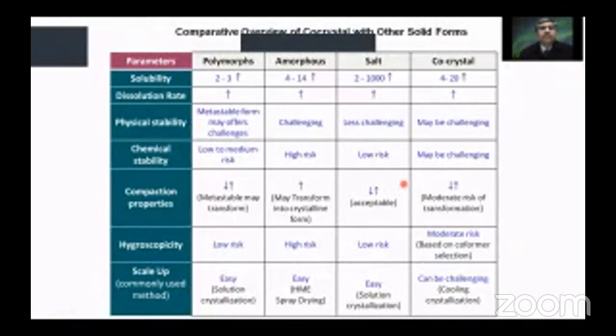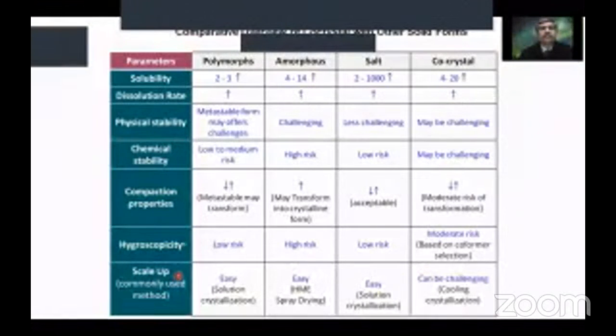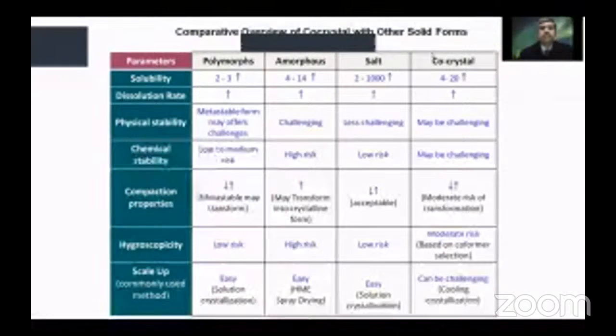This table shows the comparative overview of co-crystals with other solid forms in respect of various parameters like solubility, dissolution rate, physical stability, chemical stability, compaction properties, hygroscopicity, and the challenges during the scale-up of the process. In the case of polymorphs, a 2 to 3 times improvement in solubility is possible, while in the case of amorphous, it is 4 to 14 times. Salt forms can give 2 to 1000 times improvement in solubility. Co-crystals can give an improvement in solubility of 4 to 20 times.